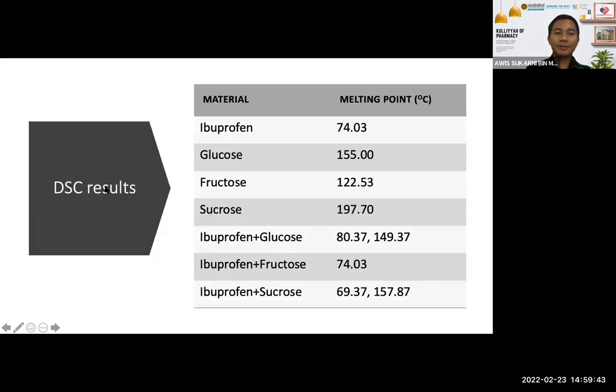After that, we ran the DSC to see if there is any change in the melting or the Tg of the sample. Because when you mix the drug with the material, especially the sugar, there is a tendency for the transition temperature to be shifted compared to the original melting point. So if you can see here, for the ibuprofen, the melting point is around 74 degrees Celsius. For the glucose it is 155, fructose 122 degrees, and sucrose 197 degrees.